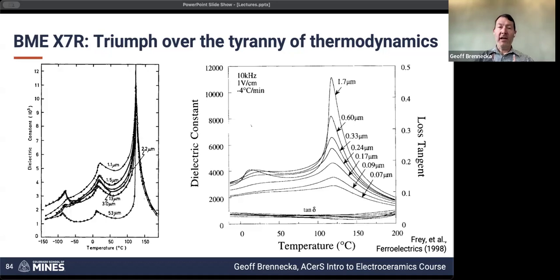And it turns out that it's a combination of the grain boundaries themselves not being as high permittivity, so they are disordered, and you don't get as strong a response to an electric field in those materials at the grain boundary. And the domain structure that we saw on the last page, where we had those twin structures, because the boundary between those, I mentioned, is basically frustrated. The boundaries themselves end up giving you a significant increase in the relative permittivity because they're sitting there sort of cubic-ish, and so they're analogous to sitting right at this phase transition between tetragonal and cubic.